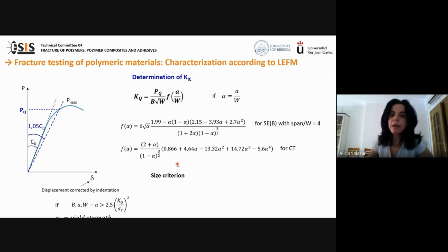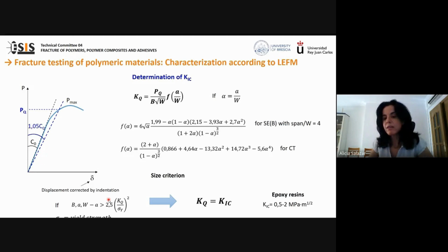Finally, the validity of KQ must be checked by the size criterion. The thickness, the crack length, and the ligament length must be higher than this value, where the square of KQ over the yield strength is proportional to the plastic zone size. If this criterion is fulfilled, then KQ is equal to K1C. Otherwise, the test is not valid. Typical values for brittle solids such as epoxy resins are in the range between 0.5 and 2 megapascals square root meter.